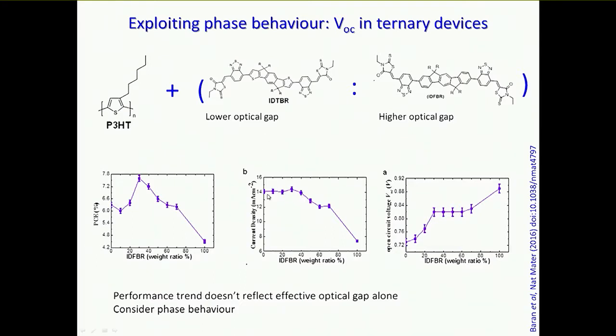So from the solar cell, we could see that as we put more of the higher gap component into the lower gap one, we would monotonically change the JSC, and that perfectly follows what happens with the optical absorption. But what happened with the open circuit voltage was slightly more interesting because it showed two phases. It shows a jump up, then it stabilizes, and then it shows another jump up. Because of this non-monotonic behavior of the VOC, and because efficiency reflects current times voltage, there was a peak. So there was a composition of the ternary which was better than either of the terminal points, and the solar cell efficiency was better.